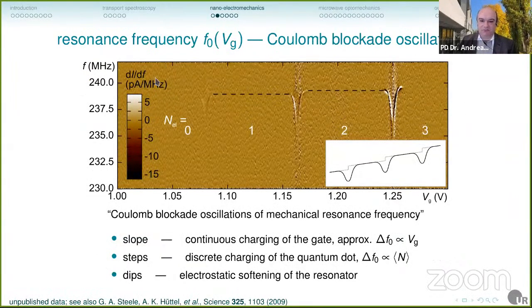We somehow never really got around to publishing this particular graph here, but it's a very nice one. You can see here the mechanical resonance frequency. It's very faint, but here it gets already stronger. This is the mechanical resonance as a function of the gate voltage across the first Coulomb oscillations, from the band gap to 1 electron trapped in the system, to 2 electrons, to 3 electrons trapped in the system. And if you look at an electrostatic model, you end up with 3 effects. One is a slope, one is a step, and one is a dip. The slope corresponds to the continuous charging of the gate electrode. You are increasing the gate voltage. The charge on the gate electrode is increasing in a continuous way, and thereby you are continuously increasing the tension in your system and the mechanical resonance frequency.